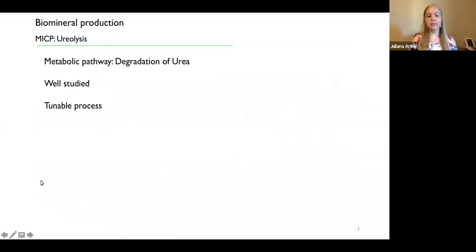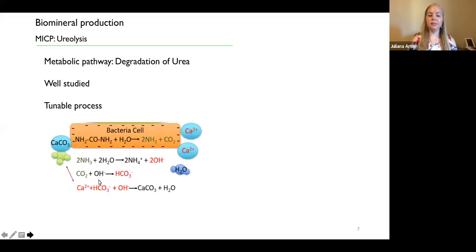We were specifically interested first in ureolysis, which is the degradation of urea. This is one of the most well-studied pathways in biomineralization. It's so well studied that if you Google ureolysis, it will give you MICP production. The advantage of this process is that since we know very well the enzyme clusters involved, we can tune how these enzymes are active inside the bacterial cell, which leads to an indirect change of the environmental pH and precipitation of calcite. It's most common and well described in heterotrophic organisms, so they need complex carbons to survive.